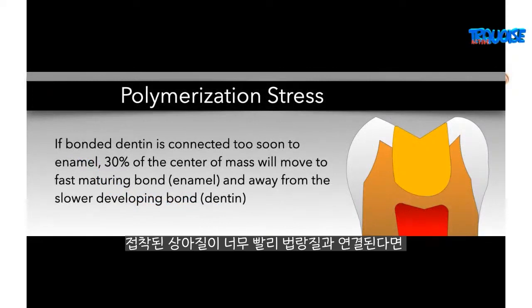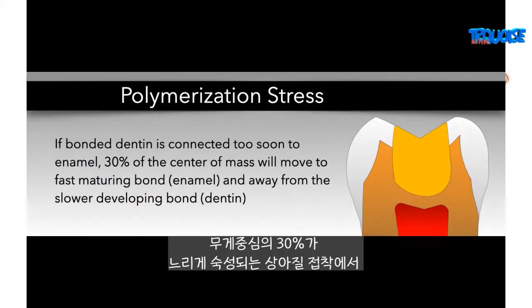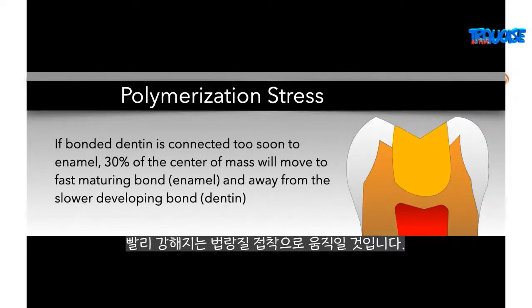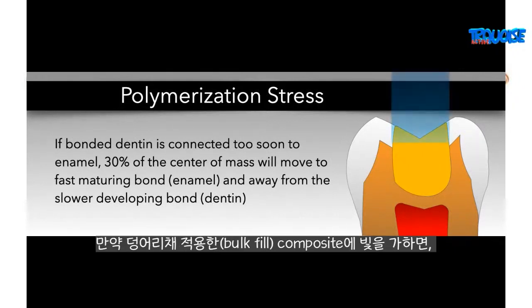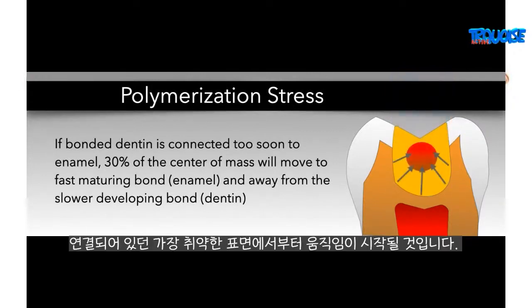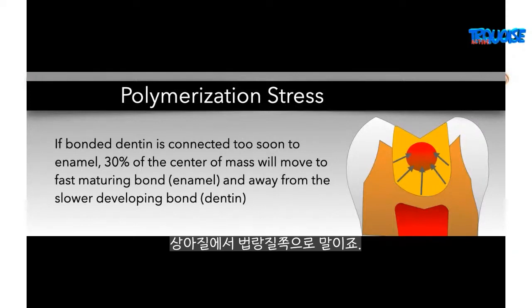So if a bonded dentin is connected too soon to the enamel, then 30% of the center of mass will move too fast, moving to the fast maturing enamel bonds and away from the slower developing dentin bonds. So that light, once it goes on to the composite, it starts moving towards the most bondable surface that all of the mass is connected to at that time, which in a bulk fill situation would always be towards the enamel and away from the dentin, and that would weaken the bond to dentin.